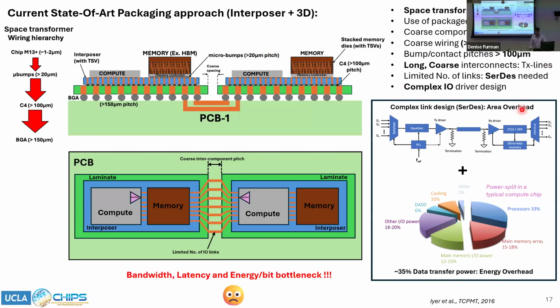And you have very complex link designs, such as the use of SerDes, that add a significant area overhead to the chip itself. For example, SerDes can add around 30 to 35% area overhead. Similarly, they also add a power overhead. In most of these systems, the data transfer power in going from, for example, compute to memory can be around 30 to 35% of the entire power consumption of the system.